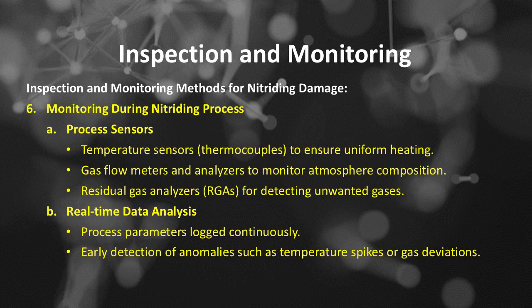Number 6 of the inspection and monitoring methods for nitriding damage is monitoring during the nitriding process. A: process sensors, including temperature sensors, thermocouples, to ensure uniform heating, gas flow meters and analyzers to monitor atmosphere composition, and residual gas analyzers, RGAs, for detecting unwanted gases. B: real-time data analysis, with process parameters logged continuously for early detection of anomalies such as temperature spikes or gas deviations.